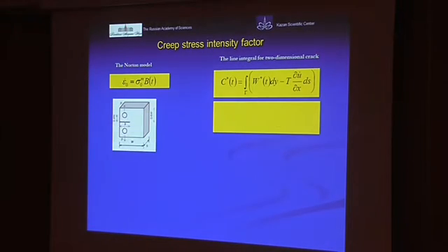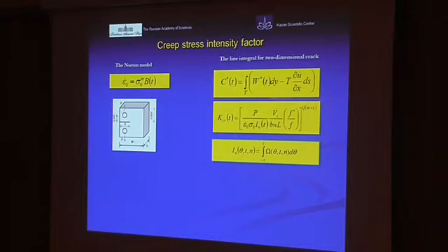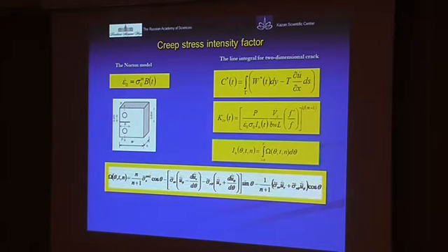The next figure shows the creep stress intensity factor equation, where the creep stress intensity factor is a function of creep time and rate of displacement in the loading direction, and again a function of governing parameters at the crack tip in the creep condition.